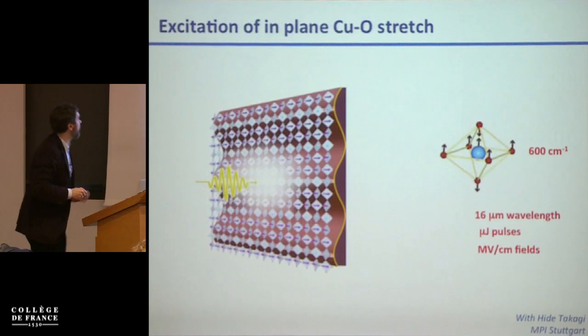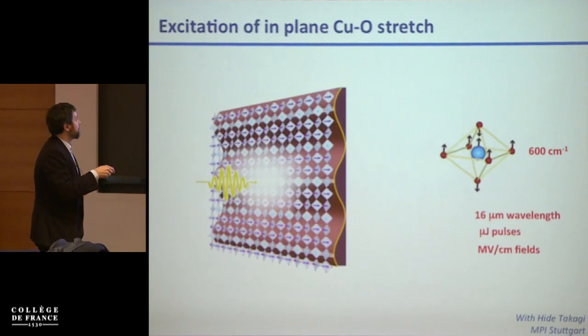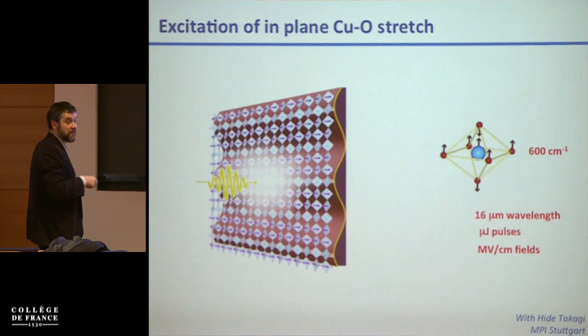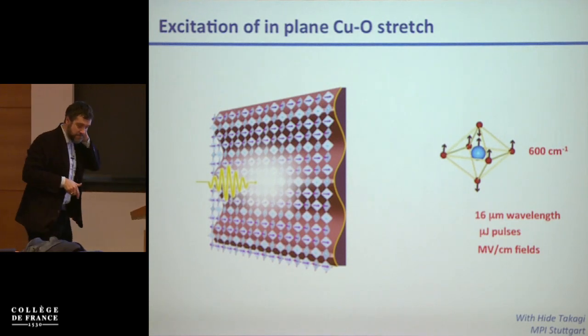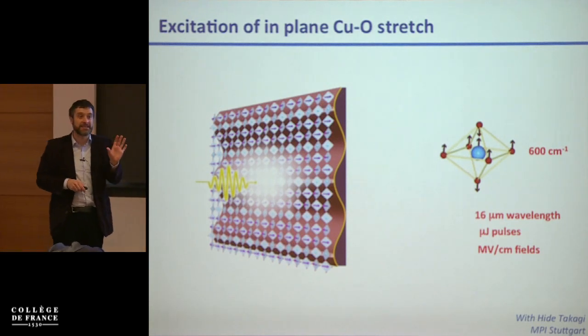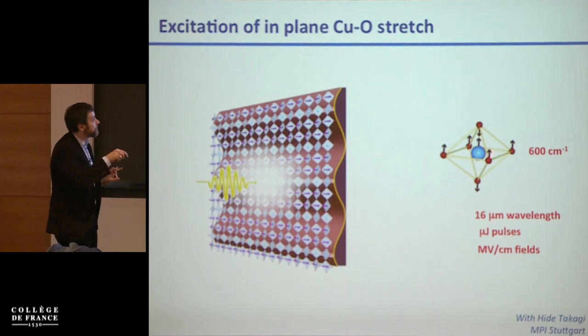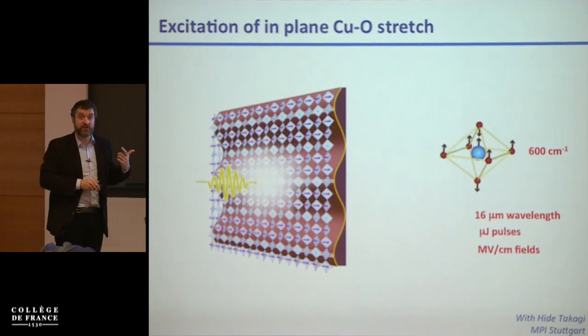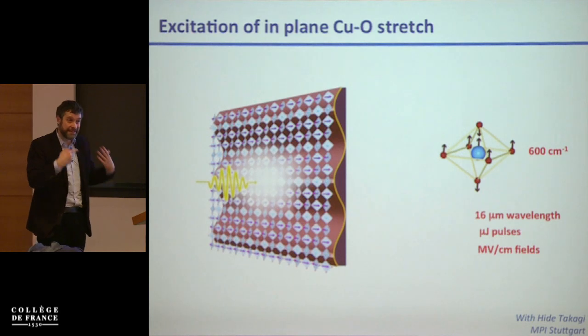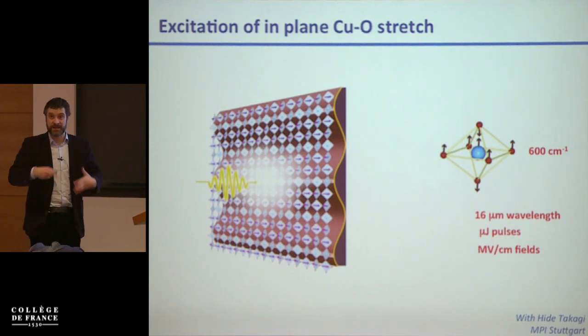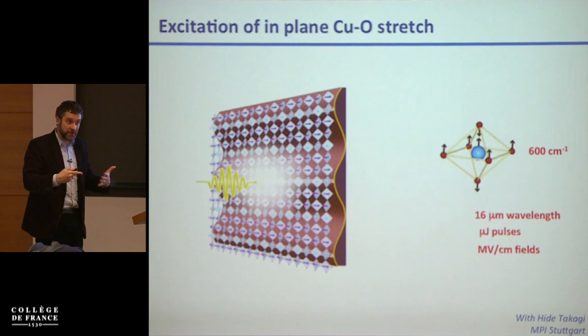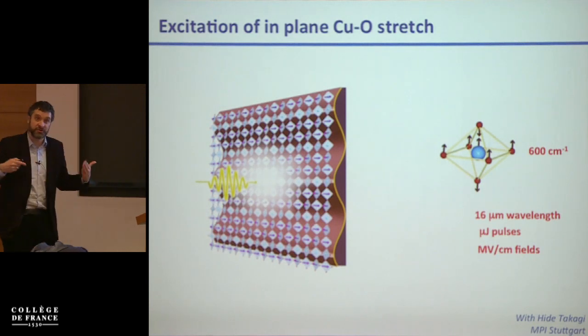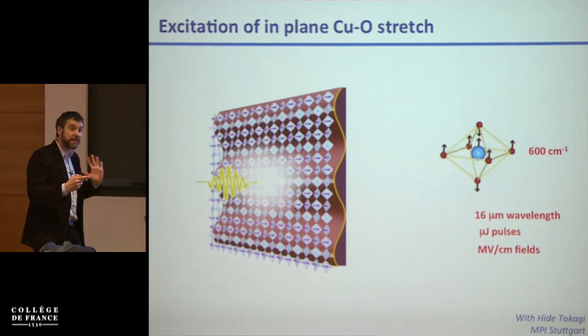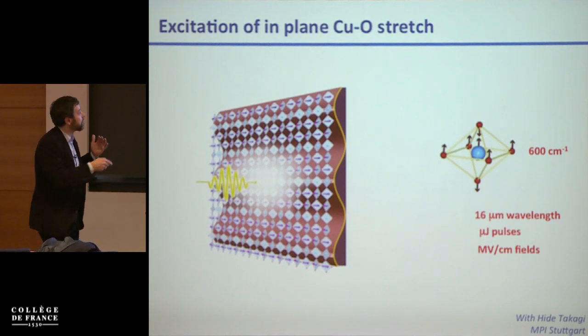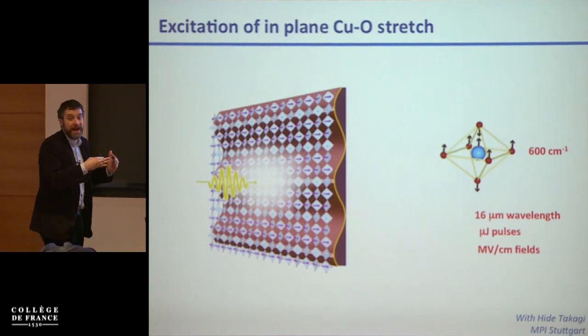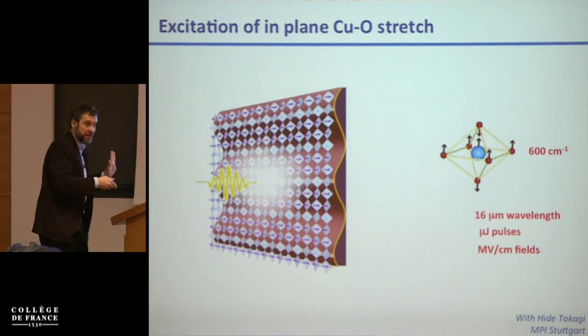Okay, so the way we started doing experiments was by pumping, again, one of these high-frequency stretching modes. As I mentioned in the first lecture, there are technical reasons why up to now we've only pumped these high-frequency modes close to 600 wave numbers. This has to do with our ability to generate laser sources which are intense enough at the right frequency to drive whichever mode we want. The situation is changing, but for many years we've effectively only been able to excite modes at frequencies of 600 wave numbers or higher. So that's why we've only excited these modes up to now.